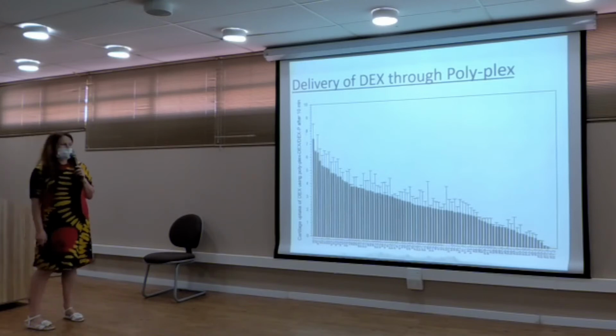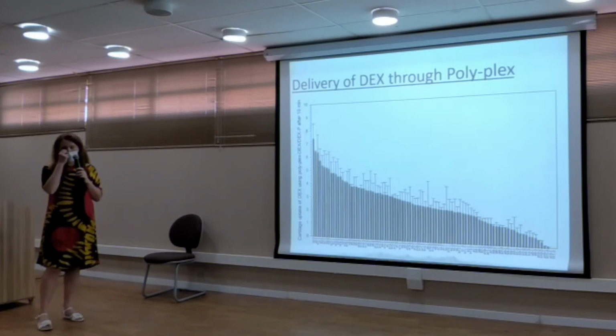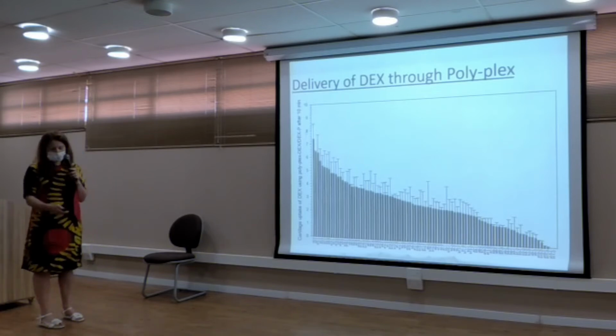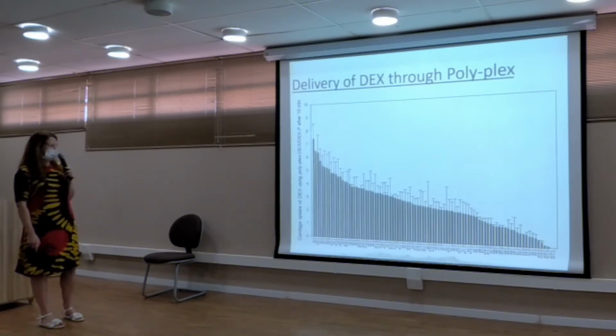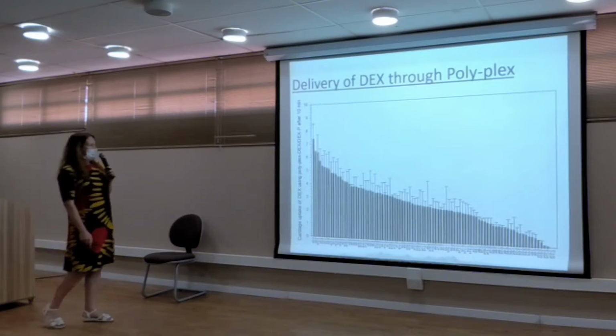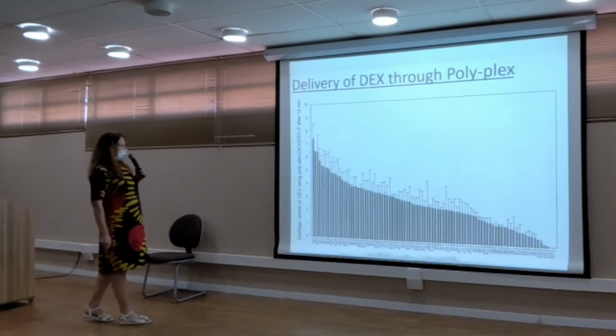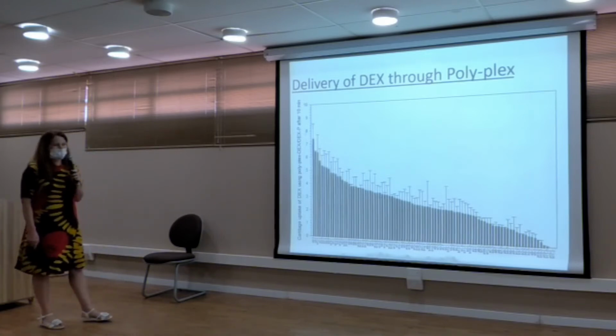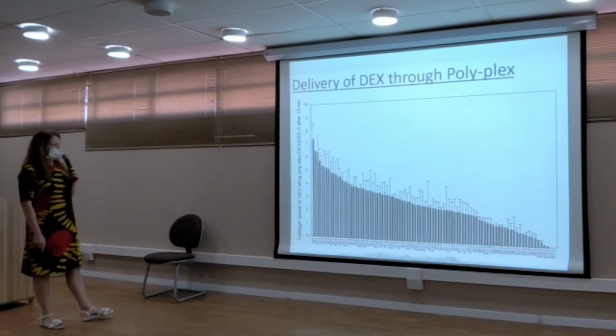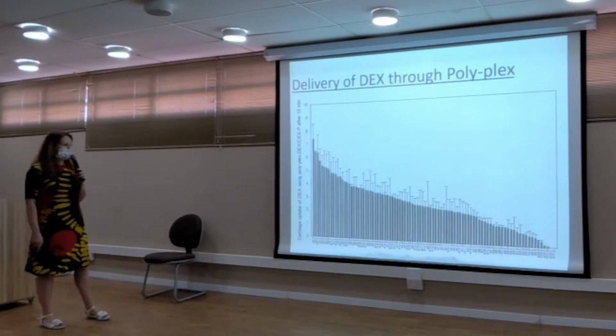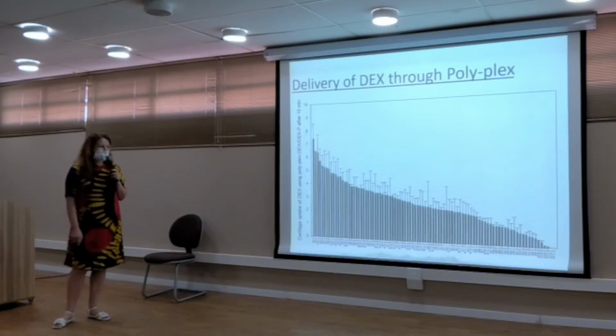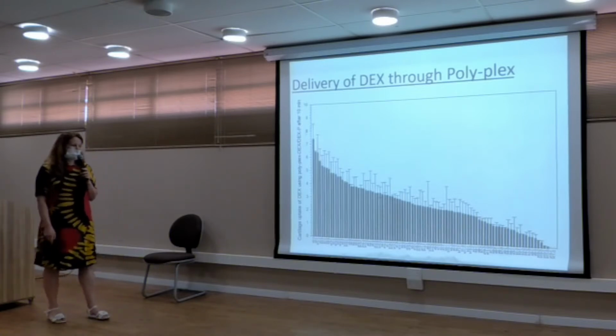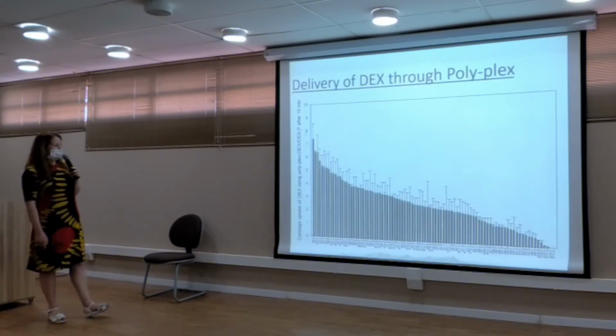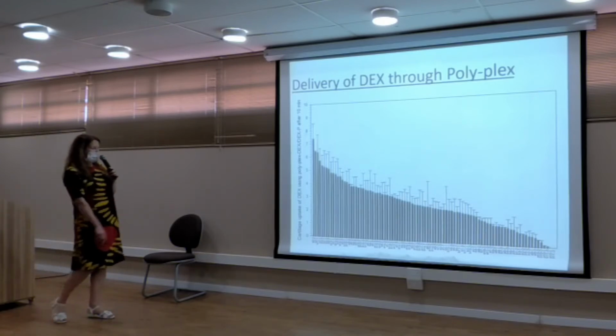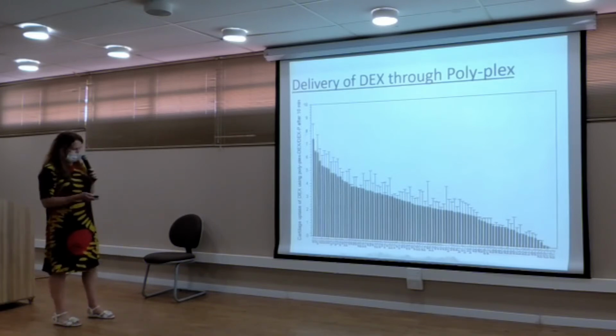Almost all these structures work in terms of enhanced uptake and retention of the dexamethasone in a cartilage matrix. As you can see here, the uptake is increased by 7-8 times compared to the commercial formulation, which we use as a control. Only some structures did not work as well. They were still preferential compared to the commercial formulation. They still give enhanced uptake, but not as significant as some of the other formulations, as you can see in the beginning of this graph.